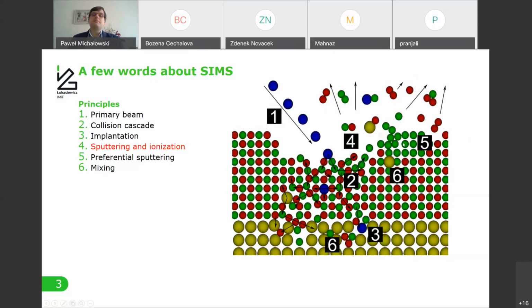Some particles may leave the sample, and a small part of them, usually below 1%, are additionally ionized, either positively or negatively. These secondary ions undergo mass analysis, and we can then detect what types of atoms were in the sample. There are, however, other effects which make the interpretation a little bit difficult. One is preferential sputtering. It basically means that one type of atom may have a completely different probability of being sputtered from the sample, and thus we may form regions, as marked here, where we see a depletion of one type of atom and agglomeration of the other.